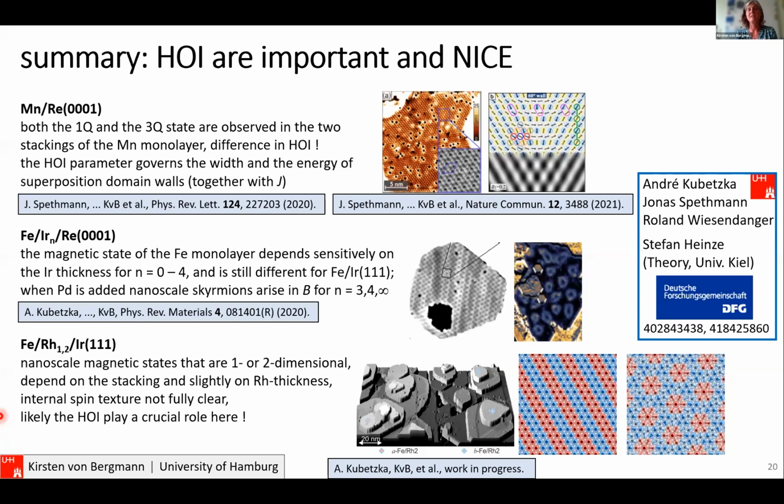If we need a tip that changes the magnetization direction in an external magnetic field, then we, for example, use a very thin iron-coated film. All our STMs are designed to take out the sample in situ and transport it to a heating and deposition stage and put it back into the STM. That's how we can have an iron-coated tip, which we can control by external magnetic fields.